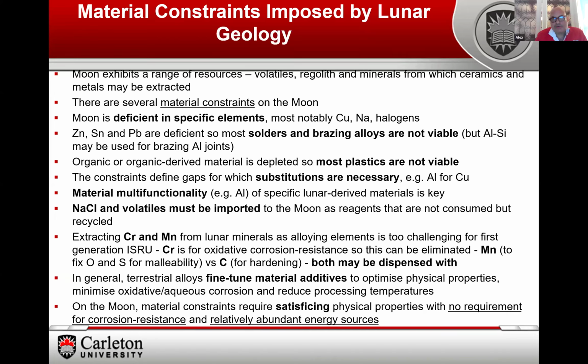But there are several constraints on the moon. It's deficient in certain elements, most notably copper, sodium, and halogens. And indeed, zinc, tin, and lead are also deficient. So this has impacts for things like solders and brazing alloys. In addition, there's very little organic material, so we can't utilize plastics on the moon because we can't manufacture them from local resources. So these constraints define gaps where we can perhaps make substitutions.